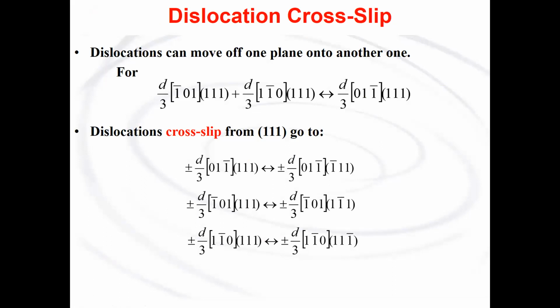These dislocations can move off one plane onto another by cross-slip. So the 01̄1 dislocation can cross-slip over to the 1̄1̄1 plane. The 1̄01 can cross-slip over to the 11̄1 plane, and the 110̄ can cross-slip over to the 111̄ plane.